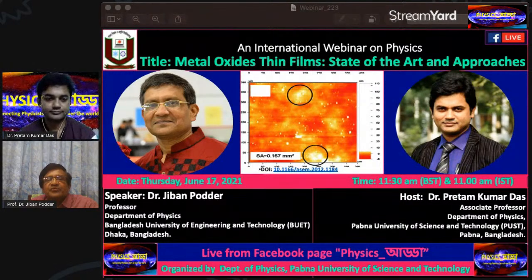A too low concentration cannot distribute over the whole film surface. But at 4% we found the optimum to accumulate within the interstitial sites and substitutionals in the space, making a good alloy. If we use more concentration, that makes more defects, and those defects cause the increase of the band gap. To reduce the band gap, we have to control the nucleation sites. So the minimum concentration and optimum concentration.